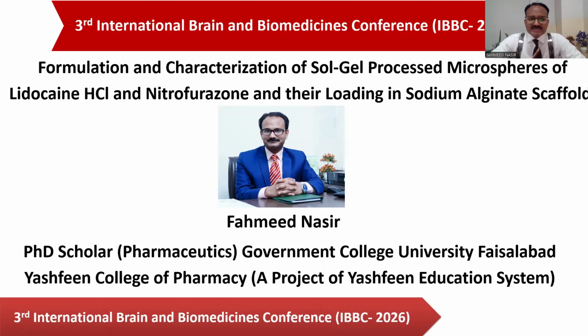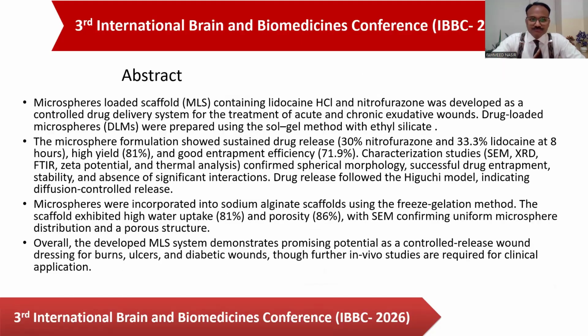My topic is formulation and characterization of sol gel processed microspheres of lidocaine HCl and nitrofurazone and their loading in sodium alginate scaffold. In this project, I used two APIs. One of them is lidocaine HCl, which is a local anesthetic for pain relieving effect, and nitrofurazone exhibits the antibacterial effects. And microspheres were prepared by the sol gel method, which contains ethyl silicate.